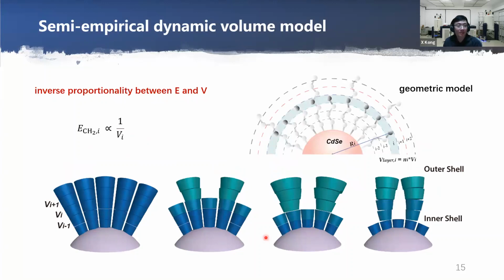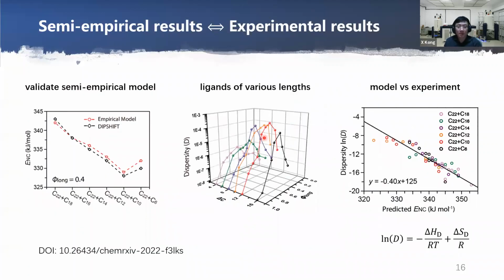So the above dynamic volume analysis relies on the dip shift experiments. But can we predict the interaction energy without NMR measurements? Here we derived a geometric model of the dynamic volume for surface ligands. The dynamic volume of each carbon unit is shown as the disks here. The bigger the volume, the weaker the interaction. The model considered the influence of ligand length and also the ratio, using empirical parameters according to the measurements of only a few representative samples. So this semi-empirical model shows excellent agreement with the results obtained with experimental dip shift.